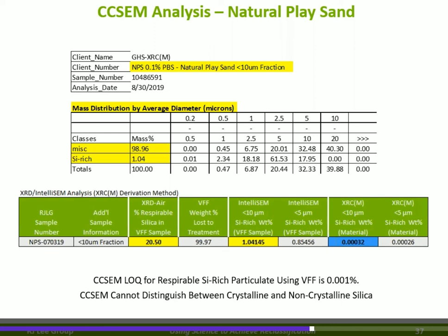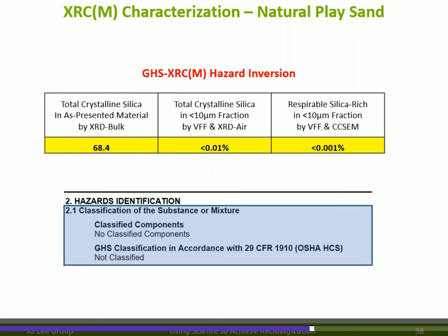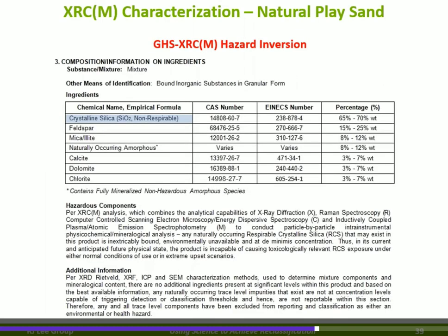Because generally what we've seen in release studies is that under 2% you get non-detect on the air filters. CCSEM cannot distinguish between crystalline and non-crystalline. However, from a conservative perspective, obviously if it isn't silica rich, it can't be crystalline silica. So our results are 68.4 in the bulk, less than 10 by VFF and XRD error is less than 0.01. Less than 10 by VFF and CCSEM is less than 0.001.